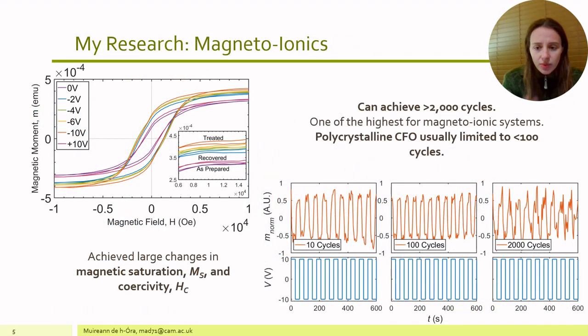And these results were really interesting. We found that we can achieve large changes in magnetic saturation and coercivity, and we also achieved more than 2,000 cycles, which is one of the highest for magnetoionic systems. Comparing with polycrystalline cobalt ferrite, which is usually limited to 100 cycles, this is really quite impressive.